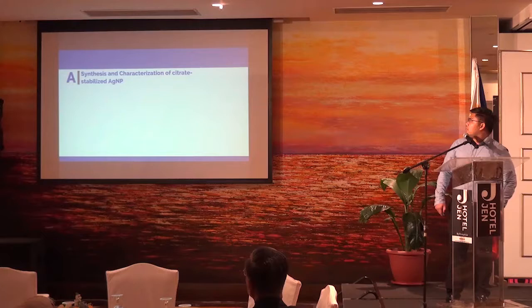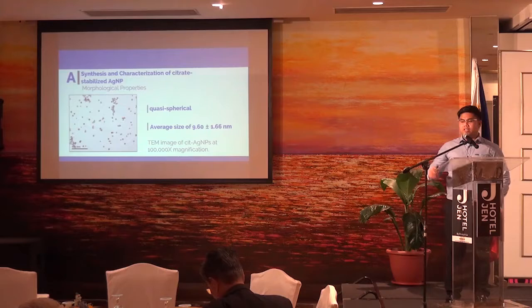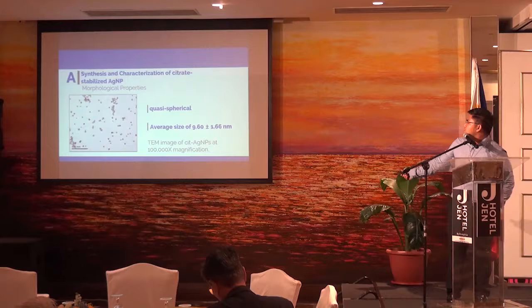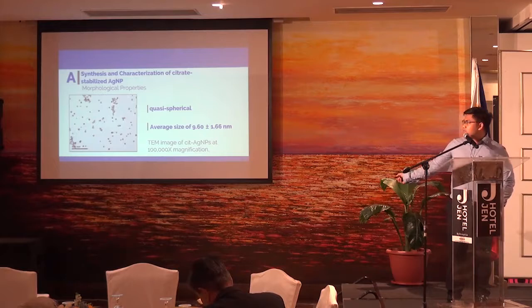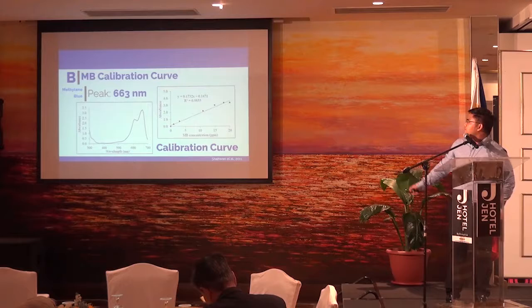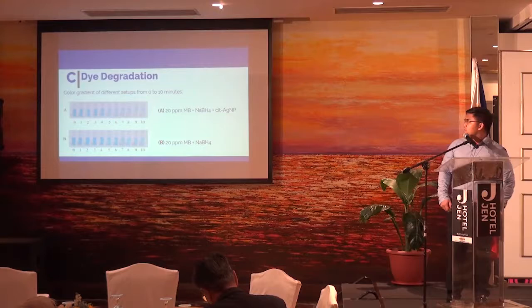This claim was further verified using TEM analysis for morphological properties. We can see that they are quasi-spherical or almost spherical in shape. The average size was obtained using image analysis software, yielding 9.6 ± 1.66 nanometers, which is near the range claimed in the study of Solomon. Next is the methylene blue calibration curve — we produced a graph of absorbance versus methylene blue concentration, which is essential to identify concentration through time for our degradation test.